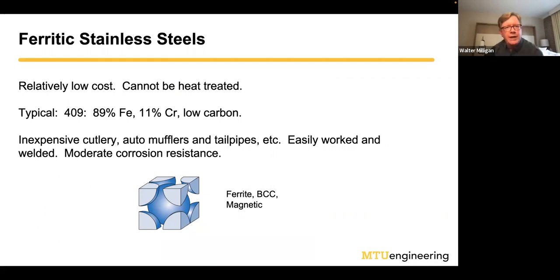And so the other 2 classes of stainless steels, the first one is ferritic. This one is relatively low cost. You can't heat treat it. You can stamp it or forge it, and you can get some benefit of strengthening by work hardening it, but it can't be heat treated. The typical ferritic stainless steel is 409. The only thing it has is 11 chrome in it. So it's 89 iron, 11 chrome. It has reasonable corrosion resistance, and so inexpensive cutlery you might buy at Walmart, for example.